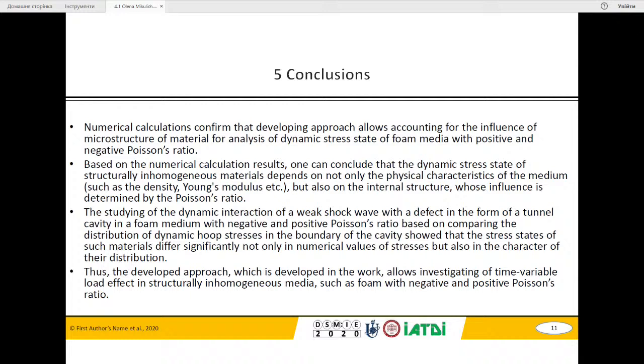The main conclusions, according to the obtained results, are in the slide. Among them, I want to make an accent on some aspects. First of all, numerical calculation confirms that the developed approach allows accounting for the influence of microstructure of material for analysis of dynamic stress state of foam materials with positive and negative Poisson ratio. Second of all, based on numerical calculation, dynamic stress state of structurally inhomogeneous materials depends not only on the physical characteristics of the medium, such as density and Young modulus, but also on internal structure, whose influence is determined by the Poisson ratio.